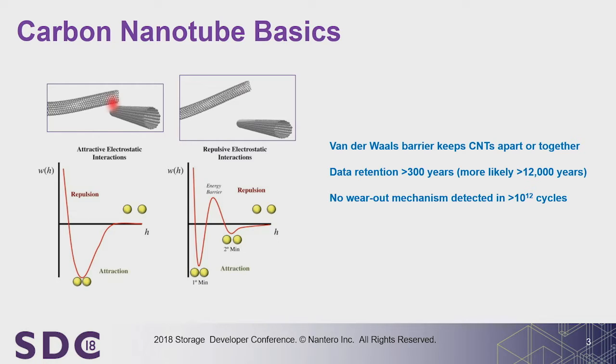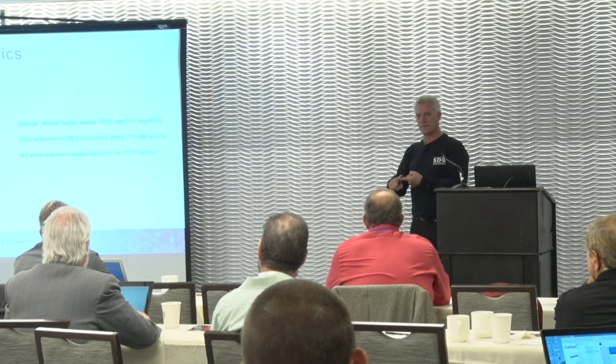We've also seen no wear-out mechanism, and it's for the same reason. One of the things that we do is we have lots and lots of these tubes switching. So once these things are switched, they stay switched. The data retention of this has turned out to be really great too, because these things are going to be connecting and disconnecting in a void. There's no substrate. So it's not like filament growing or anything like that that's going to be done in a substrate. This is done just out in a void, and so these connections can be made and broken an infinite